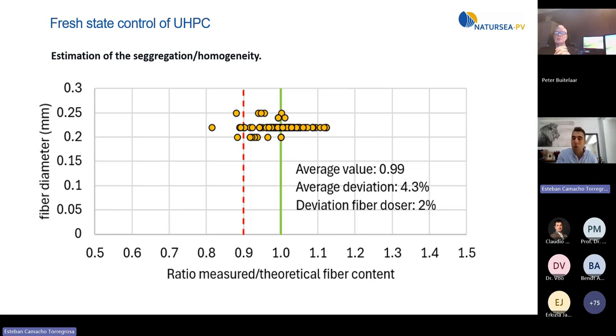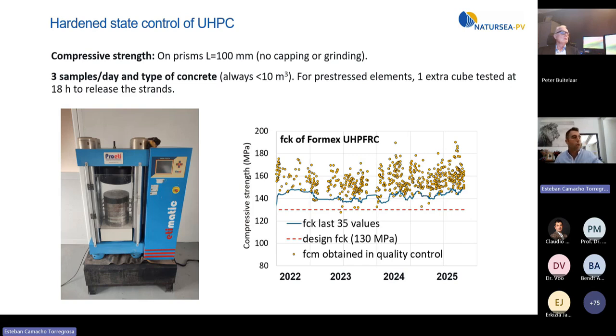And the average deviation when we measure is 4.3. However, only the variability of the fiber doser is 2%. This means that in general, we don't differ more than 2-3% in the fiber content from what we really wanted. Okay, this is the way that we use to efficiently control and quantify the homogeneity of our fiber distribution in our mixes. Well, now I go to the hardened state control of UHPC.